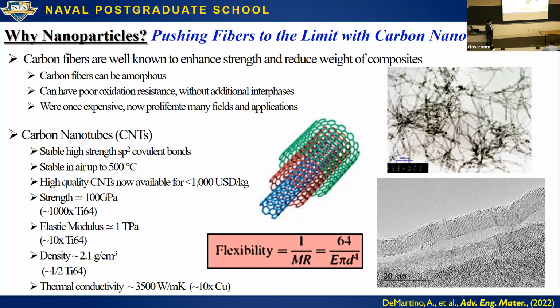It's certainly not inevitable, but it occurs very often that you get some reaction, right? So with aluminum, steel, titanium, most of those materials will actually form a carbide spontaneously, at least spontaneously in terms of thermodynamics. So if you had a single wall nanotube, you would lose all your material right away. If we have a multi-wall nanotube, we can actually afford to have a few layers react and form an interface, and we can actually get desirable interfaces sometimes. If we have just a very small amount of carbide, that's actually a very good thing for load transfer.